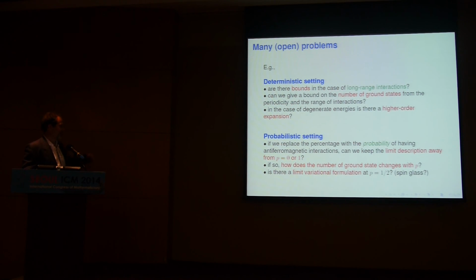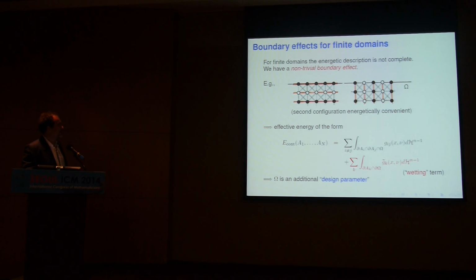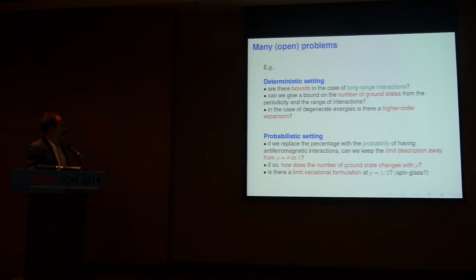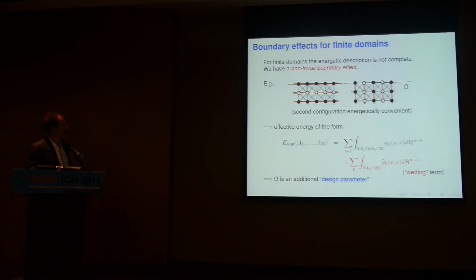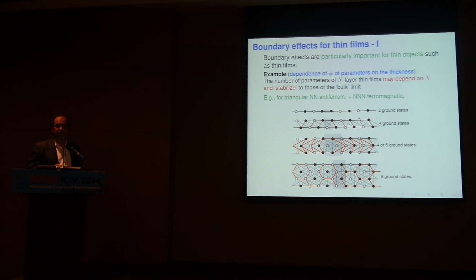Okay. I have to say that there are a lot of interesting problems. This involves also, especially in the probabilistic setting here, where we want to choose randomly +1, -1, and this microstructure also has an effect, for example, on thin films. So thin films become very interesting when you have antiferromagnetic interactions, because the number of ground states may depend on the layers. Not only does the energy density depend on the number of layers, but also the number of ground states.